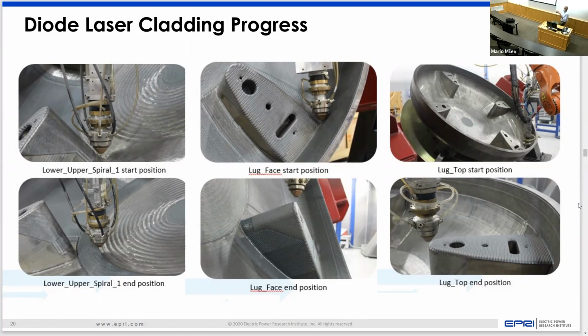So what we're trying to do is automate the process, and diode laser cladding enables you to do that. And it also enables you to put down a much thinner layer on the surface so you get less distortion overall. You can see a number of different computerized welds that have been done here, or clads that have been applied to the surface of this. What you're seeing here is actually one of the support structures that's inside of the lower head. So inside of that head, you've got to have support structures that support the rest of the reactor internals. So you can see a lot of the different welds that have been performed here.